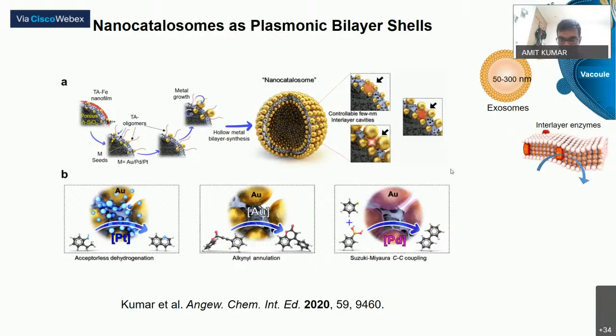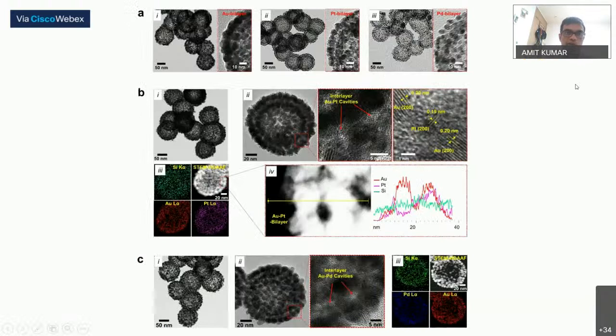And so these are the TEM images of different bilayer structures. So in the first row, there are gold bilayer, platinum bilayer, and palladium bilayer. And also, after synthesis of gold bilayer, they can be further modified with the catalytic platinum nanocrystals, very small nanocrystals. And using our methodology, we could selectively synthesize catalytic nanocrystals right in the cavity within the bilayer, the functionalized bilayer.